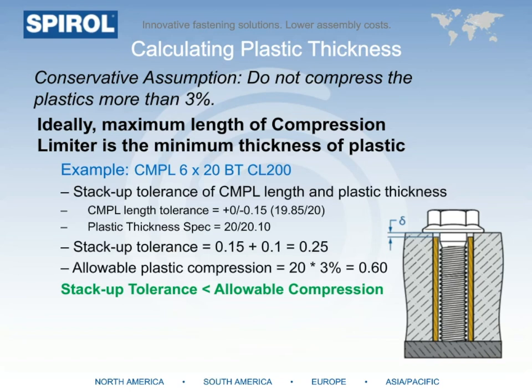To try to achieve both of these design criteria, the maximum compression limiter length should be equal to the minimum plastic thickness. In this example, we know that the length of the compression limiter is plus nothing with a minus 0.15 millimeter tolerance. Since we want the minimum plastic to be 20 millimeters, which is the compression limiter length, we would want to assign a positive tolerance on this plastic. In this example, we're assuming that the molder can maintain a 0.1 millimeter tolerance. Now that we know this, we can calculate the stack-up tolerance to be 0.25 millimeters. If we compare the stack-up tolerance with the allowable compression, or 3% over 20 millimeters, which is 0.6 millimeters, we could see that the stack-up tolerance is not going to be a problem as it's less than the amount that the plastic can safely compress.